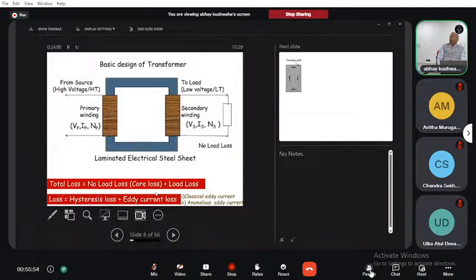One is called hysteresis loss. The hysteresis loss means you have seen that hysteresis loop, and I will also come to this hysteresis loop, and also the eddy current loss. Why is this eddy current loss there? Because we are sending a current at a frequency of around 50 hertz. So as the 50 hertz frequency is there, there will be an eddy current generated, and that eddy current loss is taking place also. To reduce the eddy current, the core what you are seeing, we make it in a lamination form. So the lamination form was made to reduce this eddy current loss.